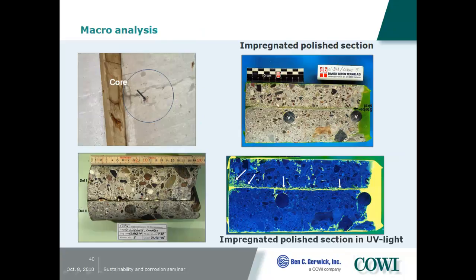This is a part of a superstructure on a bridge where there was some spalling, and we measured the cover to the reinforcement, and it was fairly big cover, no chlorides, no general carbonation. We took out cores, and we found that we had a cold construction joint in this area. And you can see it's been impregnated with a fluorescent dye epoxy under vacuum so that it will penetrate all voids and cracks in your concrete.